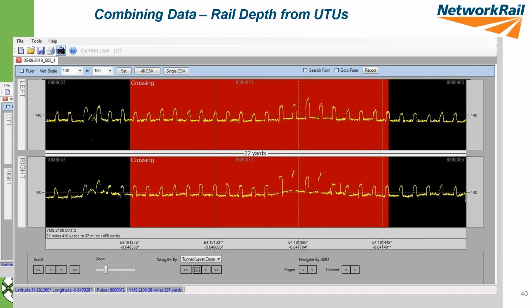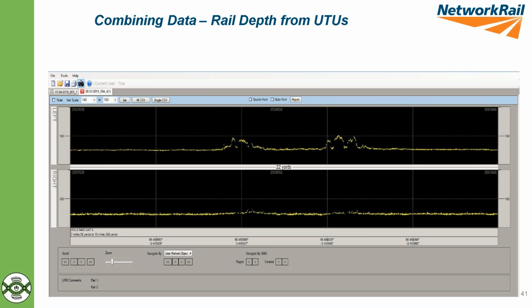But if you look at the wider data through a similar rail depth information, you can see very locally in the crossing, we've got some patches there where we've got a general loss of section, perhaps not the gall that we saw in the previous picture, but this example shows localized loss of section. That's effectively where the foot is missing and has caused a reduction in the depth of the rail. So something that looks fine on the surface, but what's happening under the crossing, for instance. But again, something that the data is there from the UTUs, it's just making sure we can present that.